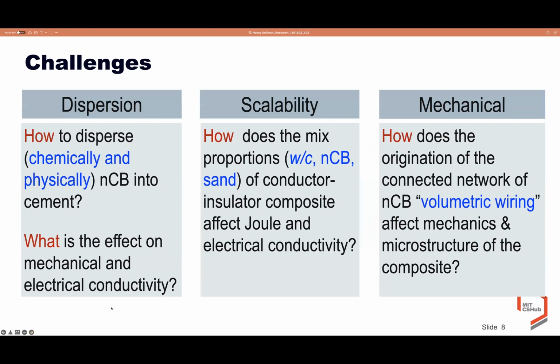But there are some challenges with using nanocarbon black in the cement matrix. The first challenge is dispersion, especially as nanocarbon black is a hydrophobic material and cement is a hydrophilic material. So how do we disperse nanocarbon black chemically and physically into cement, and what is the effect on mechanical and electrical conductivity? Moving to the second question, how do the mixture proportions and the texture of the cement matrix, such as water-cement ratio and nanocarbon black content, affect the measurable electrical conductivity and Joule effect?